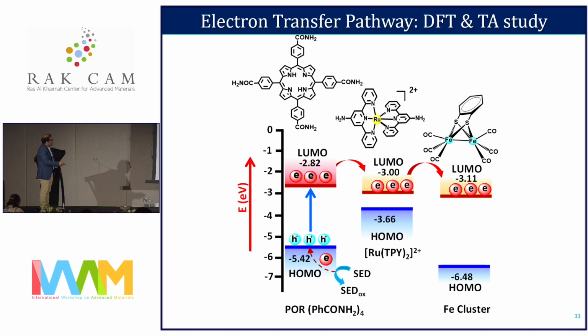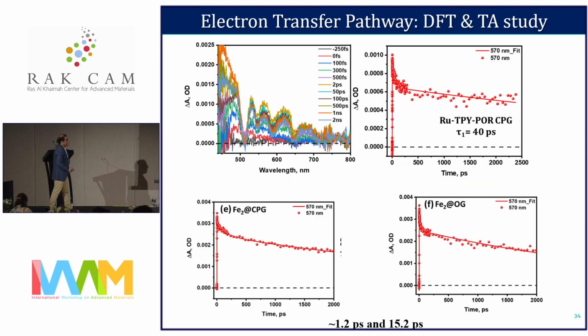From the theoretical study, we understood that from the LUMO positions of the ruthenium porphyrin core to the LUMO of the ruthenium terpyridine, then to the LUMO of the diiron cluster, there is a cascade electron transfer process, which is also supported by the transient absorption spectra.